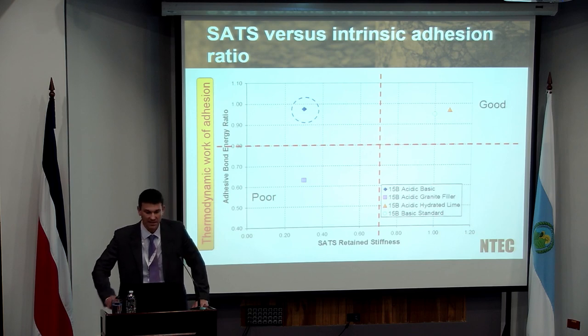As with any real set of data, there is an outlier. There is an outlier that says quite clearly that the test is indicating that this material is poor. Its field performance indicates it's poor. Its surface energy, intrinsic adhesion, and thermodynamic calculations indicate that it's actually not bad. And so I'm not proposing any one of these tests in isolation is going to give you the solution. It's how we use them as particular tools at our disposal to look at our material. So whether we go from a very fundamental approach, looking at surface energy, looking at intrinsic adhesion, looking at your energy ratios, or where you develop a test such as the peel test or the PATTI, any kind of test that's directly measuring fracture strength or fracture energy in a dry and wet condition, or whether you go through to your full asphalt mixtures.